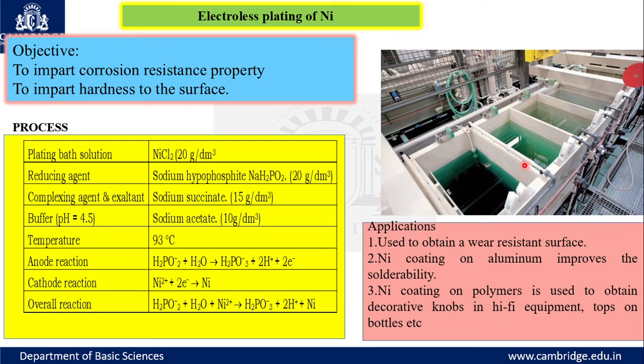And here the bath temperature is very important. The pH of the bath is maintained at 4.5 because during the course of the reaction there will be a release of H plus ions. If the concentration of H plus ions increases in the bath solution, what happens? The electrons and hydrogen ions combine to form hydrogen gas. That gas can be trapped in the atoms of the nickel, which will lead to hydrogen embrittlement. That means the coating may not be uniform, instead it has cracks. To avoid such a problem, it's compulsory to carry out the reaction at this particular pH 4.5 itself.